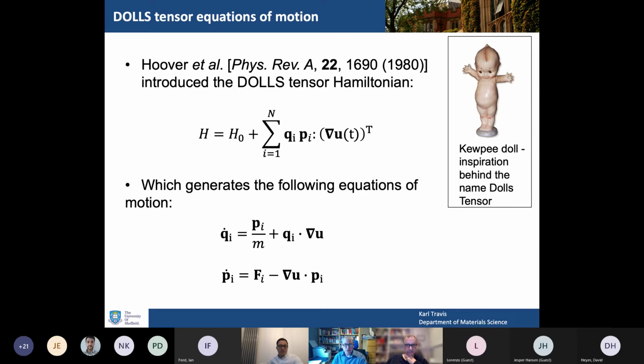But then it was soon realized that while the Doll's tensor equations could generate planar Couette flow and give the right results in the linear regime, when we went to the nonlinear regime, it didn't agree with the homogeneous shear or sliding brick method. So there's something wrong.